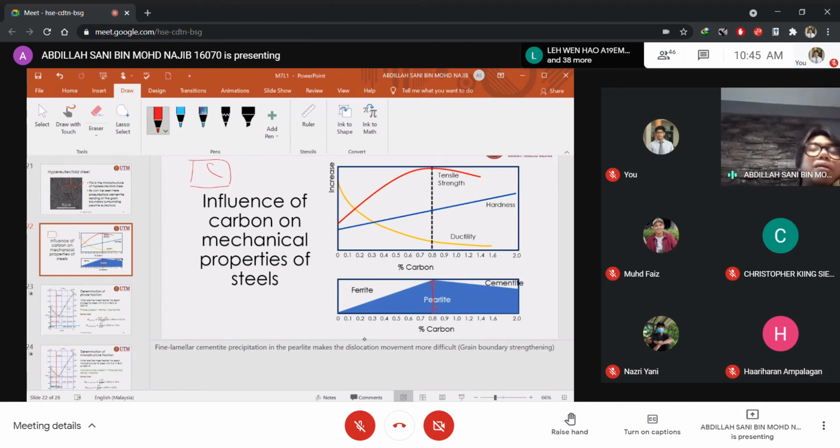If the grain is big, the interface is little, but if the grain is very small, the grain boundary has more hindrance for the dislocation to move. Likewise, when we have those lamellar structures, we have a higher amount of interfaces, and the dislocations cannot move freely, which is why it has higher strength.